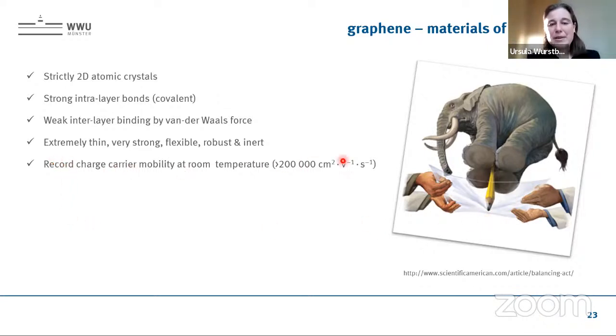Due to the relativistic charge carriers, we have a record high charge carrier mobility, and actually this comes because the electrons don't interact with the potential of the lattice, they don't even see it. So that's the reason why they move more or less relativistically through the crystal, because for them the crystal feels like vacuum.